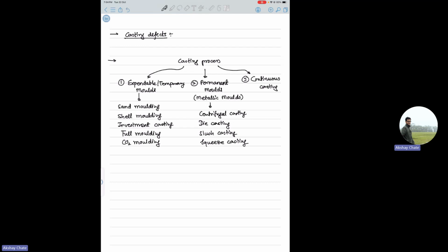Usually, you use fine dry silica sand, resins, and alcohol. You don't use water here because we operate at temperatures around 250 degrees Celsius. You put that mixture around the pattern and heat it up to 250 degrees Celsius. Then a shell forms around the pattern, you take out that shell, and you make the mold out of that shell. Shell molding is used for cylinder heads, cylinder blocks, rocker arms, all those things. So in shell molding, you don't use clay or water.